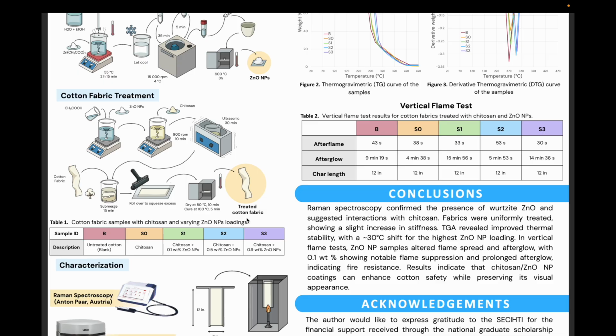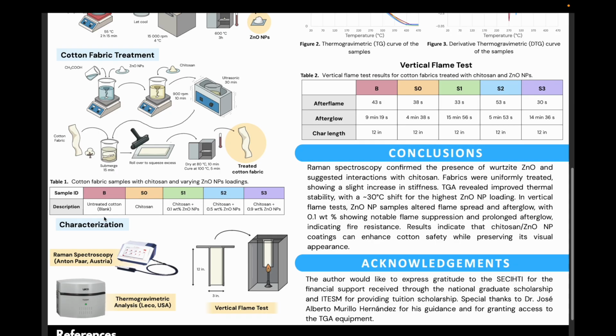In this way, treated cotton fabrics were obtained, and 5 different samples were prepared. One untreated fabric, which is our blank, one fabric treated only with chitosan, which is our sample 0. Sample 1 is chitosan and 0.1 weight% zinc oxide nanoparticles. Sample 2 is chitosan and 0.5 weight% zinc oxide nanoparticles. And sample 3, which is chitosan and 0.9 weight% zinc oxide nanoparticles.